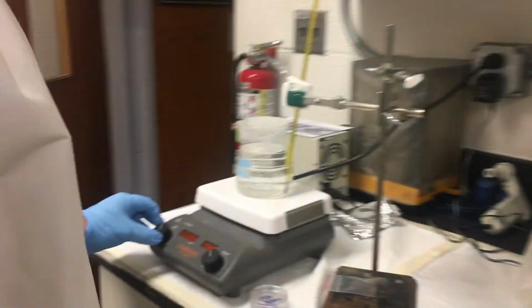Degradation testing was conducted in order to determine the rate at which our polymer would be hydrolyzed within the body. To do this, we measured mass loss over a period of time when the polymer was subjected to body-like conditions.